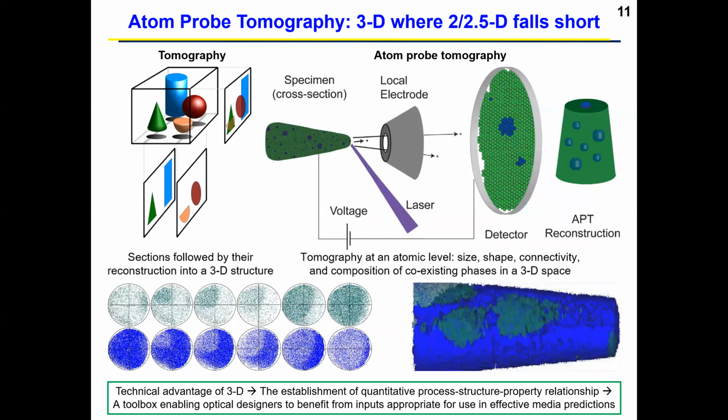So this is where atom probe tomography as a 3D tool can be introduced to fix this issue. Tomography utilizes multiple cross-sectional images collected from the target, which are then compiled back to the 3D structure of the target material. The technique allows the identification of distribution of the inclusions within their matrix, often not possible in projection methods such as TEM, where those inclusions are seen overlapping. Atom probe tomography, shortly APT, exploits this concept at the nanoscale.